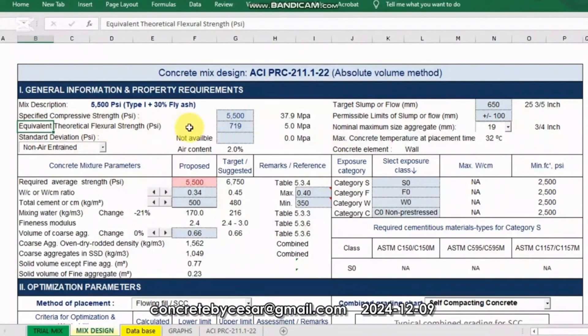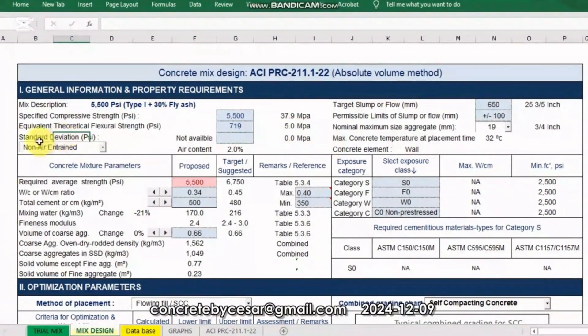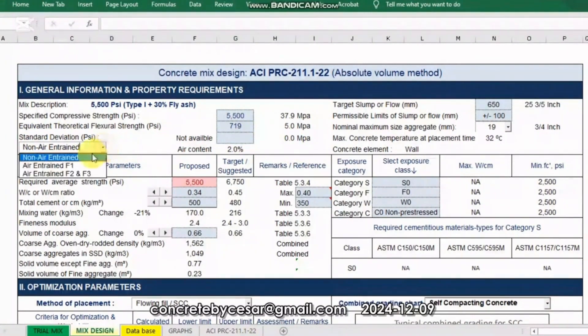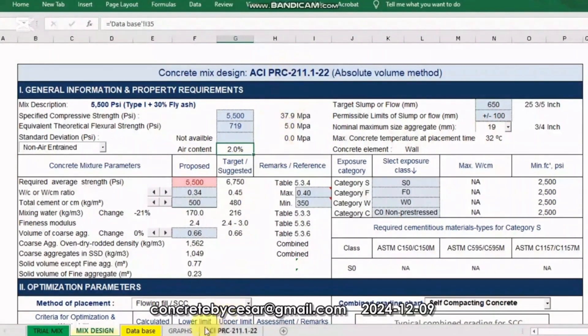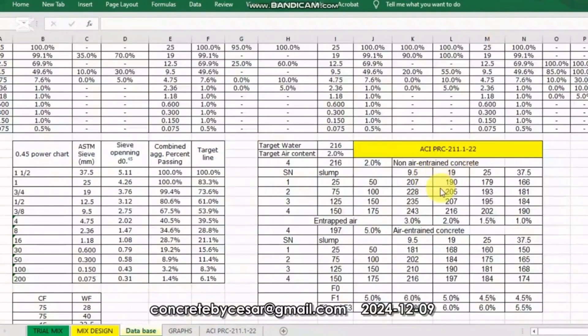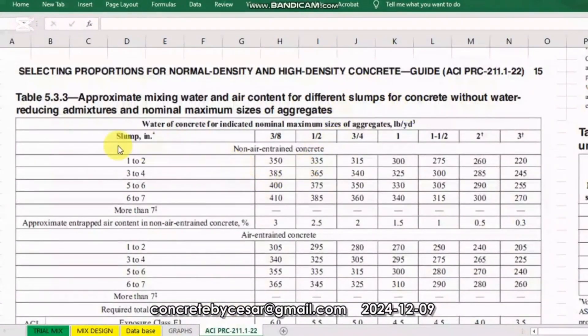The equivalent theoretical flexural strength would be 719 PSI or 5 MPa. Since we don't have a standard deviation, this will lead us to a higher strength margin, so let's keep it empty. I won't be using air-entrained concrete in this example. I will use non-air-entrained for 19mm nominal maximum size of aggregate. This cell will automatically provide 2% air content accordingly — you can verify its reference from the guidebook. From the database tab, 19mm equates to 2% air content, matching the ACI table which shows 2% approximate trapped air content for non-air-entrained concrete.